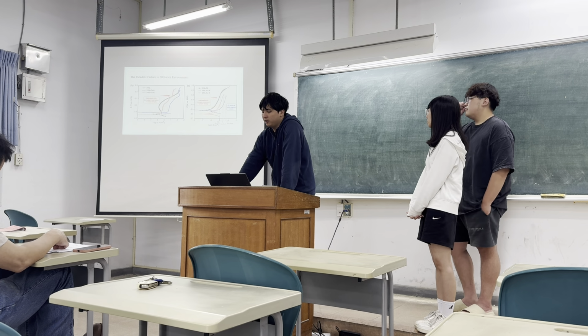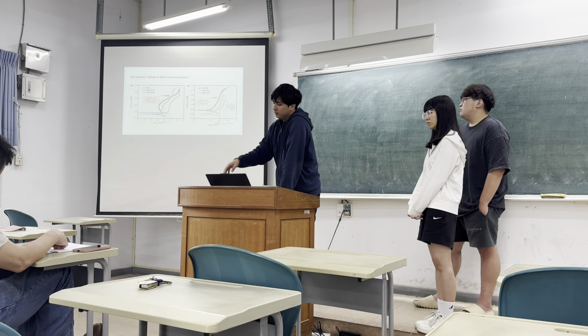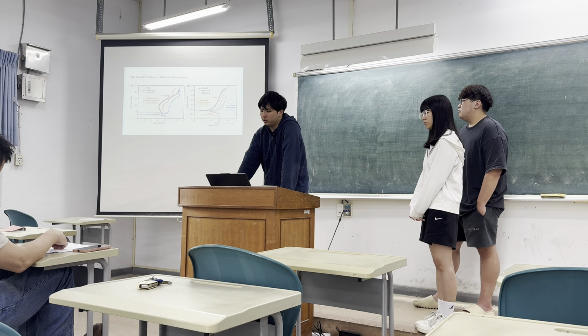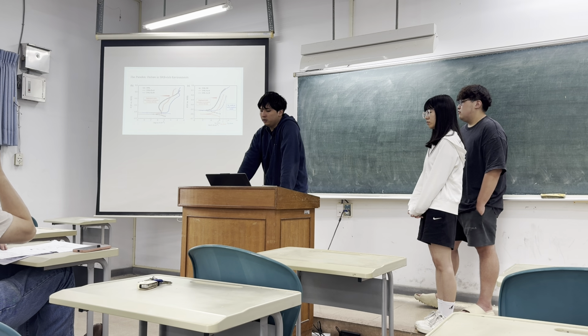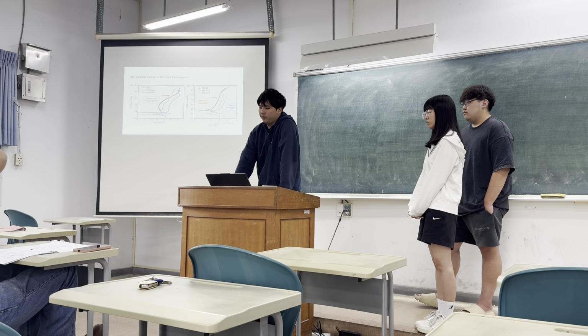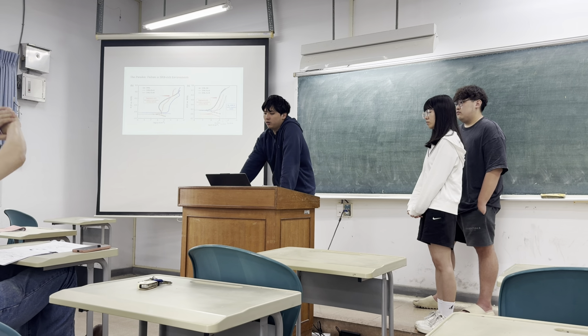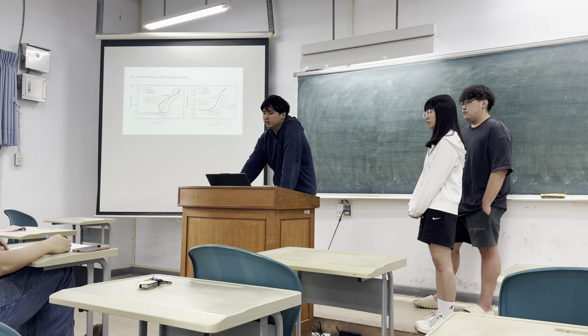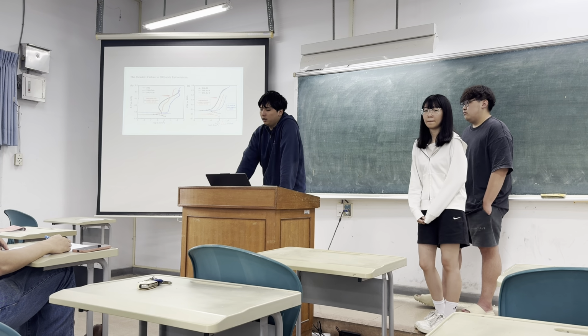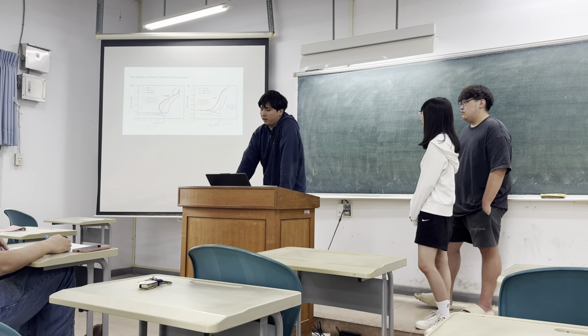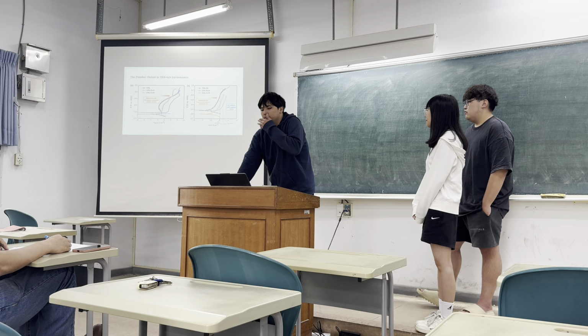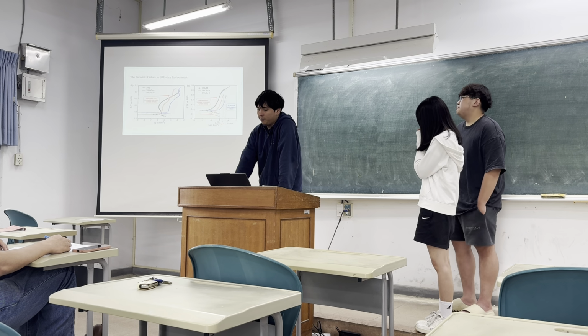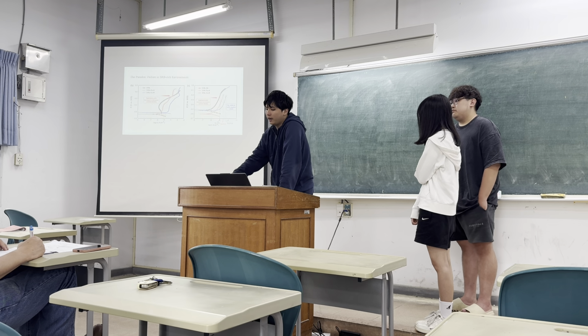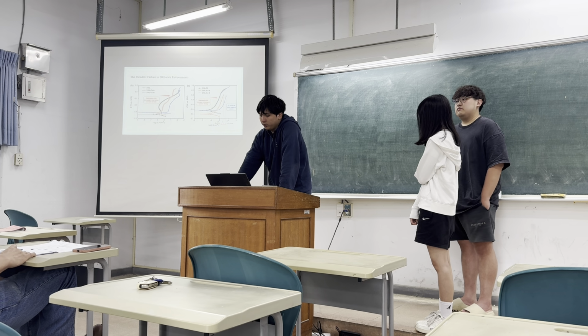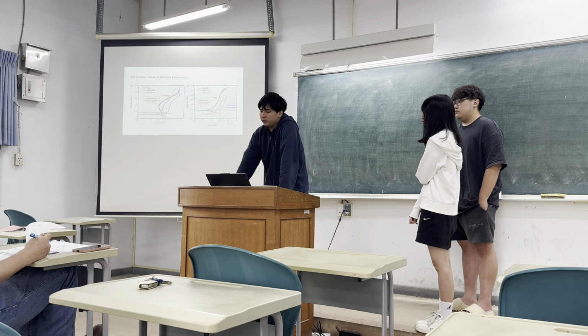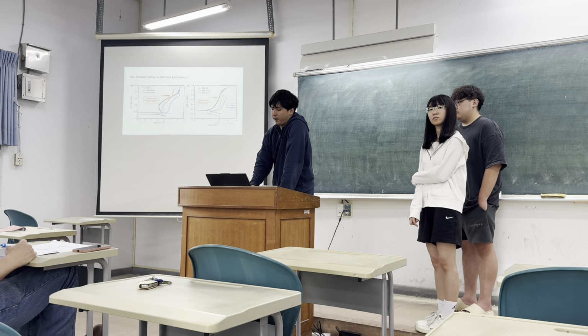Let's observe the curves in the SRB environment shown in figure B and figure C. Unlike the sterile condition, we see a distinct rightward shift of curves for all Cu bearing steel. This indicates a significant increase in the corrosion current density, meaning the overall corrosion rate is accelerating due to bacterial activity. More critically, by tracking the pitting potential, we can see it shifts to more negative values in the presence of SRB. This tells us that the passive film has become unstable. It can no longer protect the steel at higher potential, and the material becomes prone to localized pitting much earlier than expected.